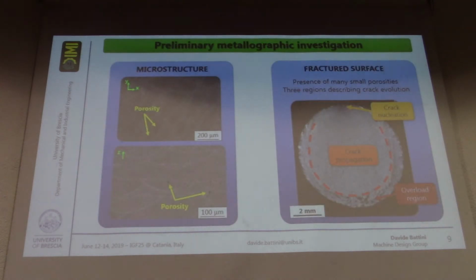So let me skip on this, we just see typical additive manufacturing microstructure. There's nothing new here. Melting pools on the in-plane images and typical half-moon melting pools on the z-axis images, as all specimens were manufactured along the z-axis. Here we can see one of the fractured specimens.